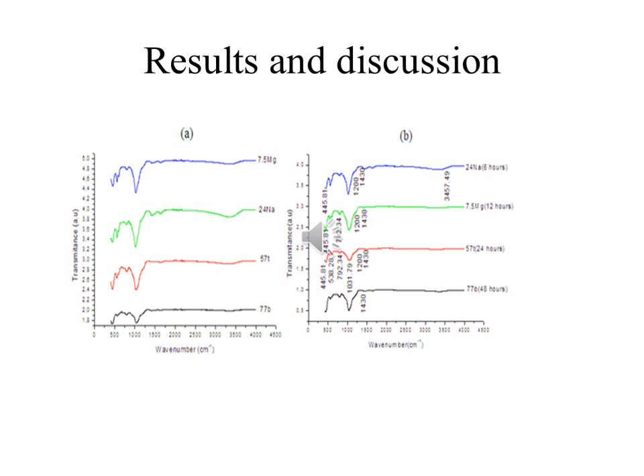For FTIR analysis, this figure shows the FTIR spectra of samples before soaking in SBF. Before soaking, the spectra of the sample exhibited Si-O-Si stretching and bending bands. The band at around 1018 corresponds to the vibrational mode of the asymmetric stretch of Si-O-Si. The band at 800 corresponds to the symmetric stretch of Si-O, and the strong band at 475 corresponds to the vibrational mode of the bending of Si-O-Si.